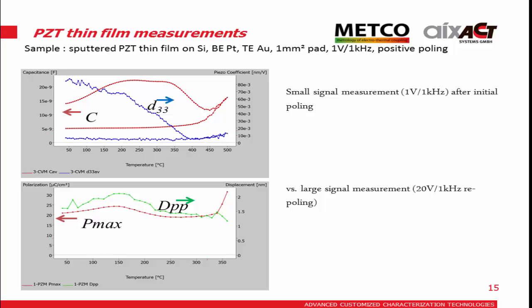We can see the small signal excitation without poling it during the application, that it's already disappeared at 400 degrees C, and it's getting electrostrictive only after that. If we apply a large signal, exciting the material all the time, we still maintain it, it broke down at 350 degrees C, but the value is more constant than here, where it drops down.